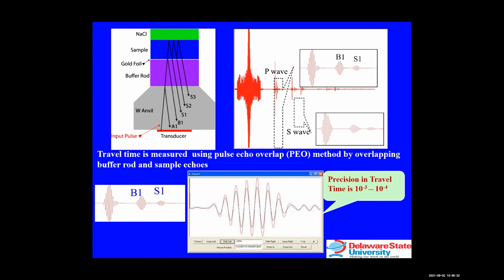So we determine the P and S wave travel time by a pulse echo overlap technique. That is by matching or overlapping the two echoes from the buffer rod and the sample cycle for cycle, as shown in the lower bottom part. The precision of this travel time measurement is extremely good, about 10 to the minus 3 to 10 to the minus 4.